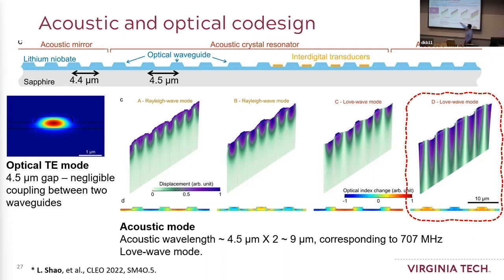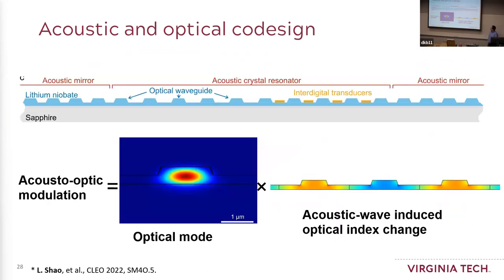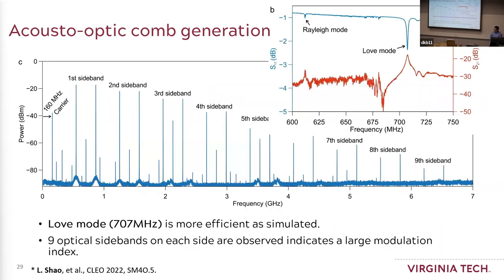You have different things to maximize this interaction. You want a good overlap between this induced index change and the optical mode. The overall acousto-optic modulation, or acousto-optic interaction, equals what the optical mode looks like multiplied by the optical index change induced by the strain field of the acoustic mode. By properly designing those two things, we can make this interaction very efficient.